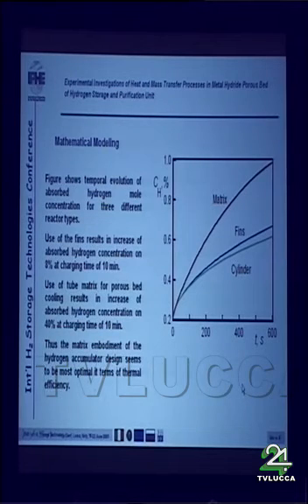So the result of this modeling shows that the use of the fins results in an increase of 8% at charging time of 10 minutes, and the use of tube matrix is 40% at charging time of 10 minutes.